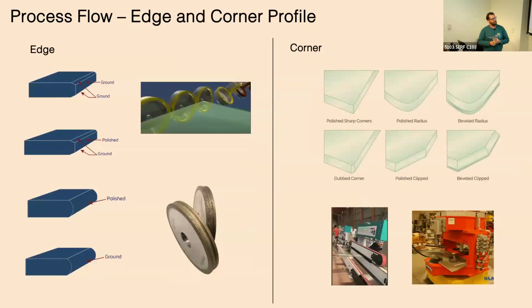When you look at edge profile, and again, this is a quick snapshot of what I did to get ready for this, there's a whole bunch of other edge profiles out there. The most common in architectural is a knocked-off edge, a polished, small little chamfer. If you see any architectural exposed glass edges, you'll tend to see this edge profile, typically polished for aesthetic reasons and some strength. The grinding wheel there is in a linear fashion. You can see the glass goes through and hits a bunch of different grinding wheels that put in the profile you're looking for.